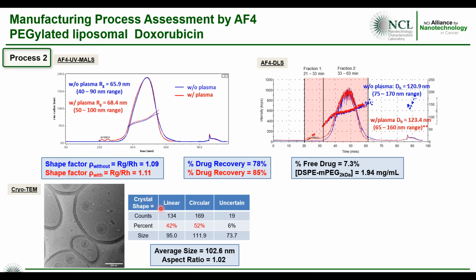And actually, because of this increased amount of circular drug, this explains why the shape factor increases relative to the previous process, because you have more of your mass distribution now to the surface of the liposome as opposed to the center. So we're now looking at AF4 as a way to look at possibly crystal shape morphology in formulations.